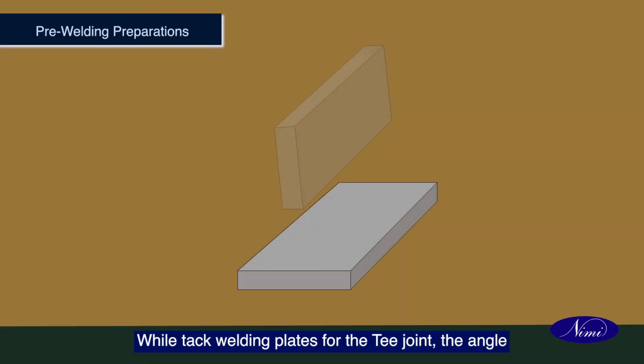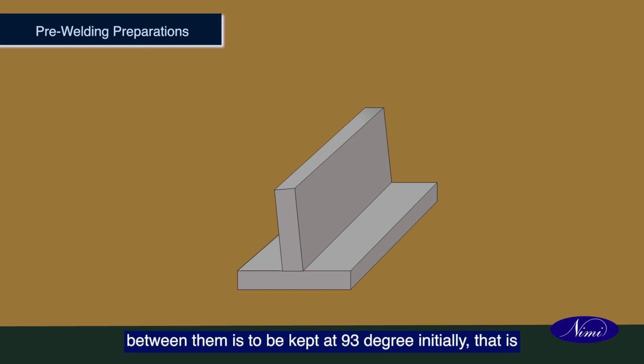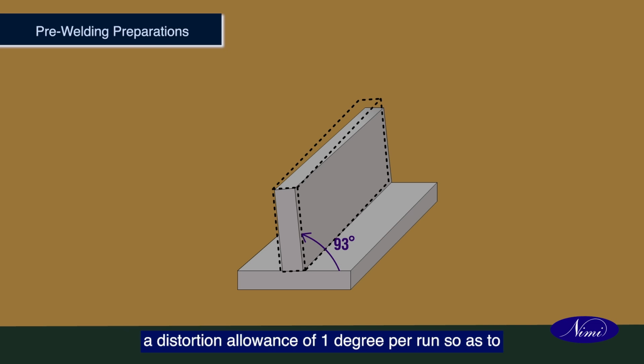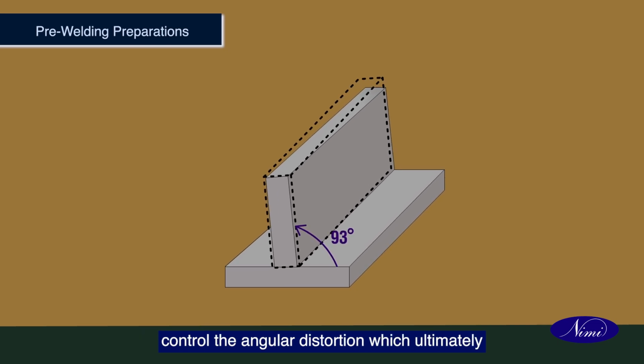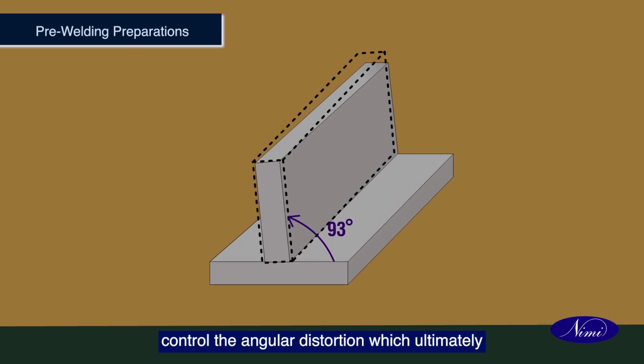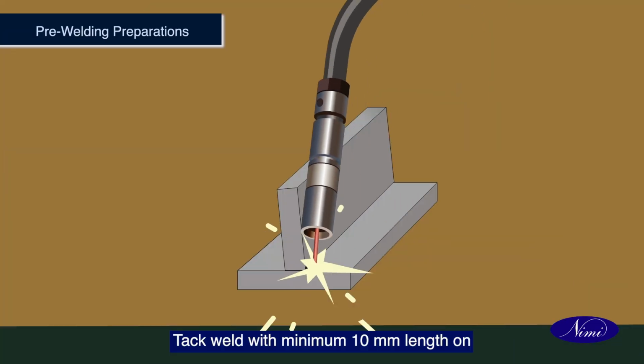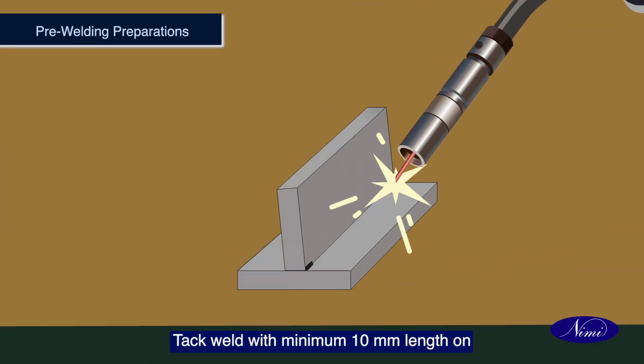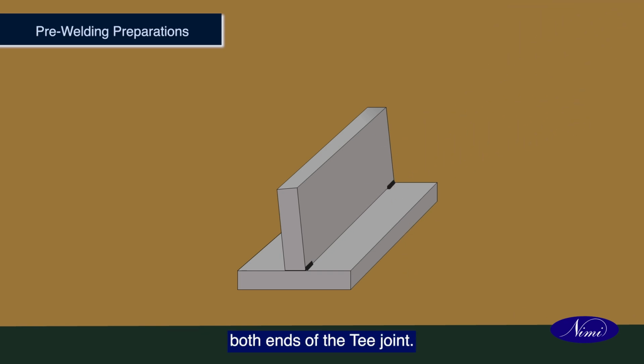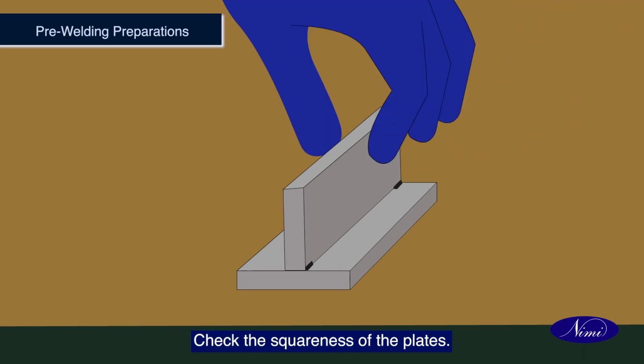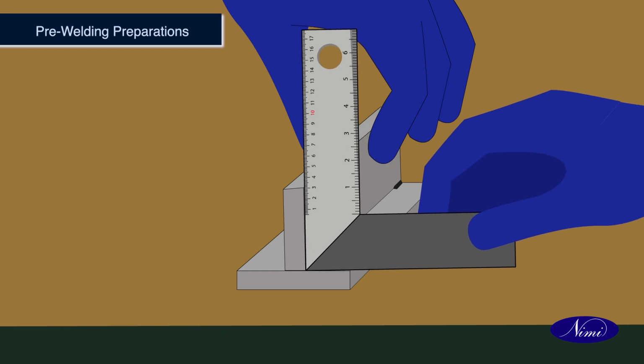While tack welding plates for the T-joint, the angle between them is to be kept at 93 degrees initially, that is, a distortion allowance of 1 degree per run, so as to control the angular distortion which ultimately settles to 90 degrees after welding. Tack weld with minimum 10 mm length on both ends of the T-joint. Check the squareness of the plates.